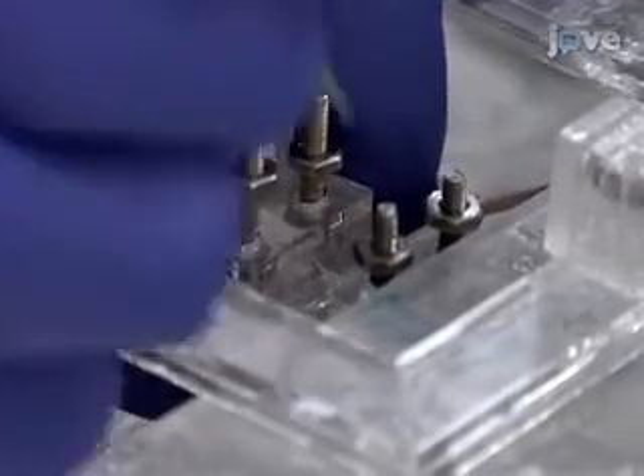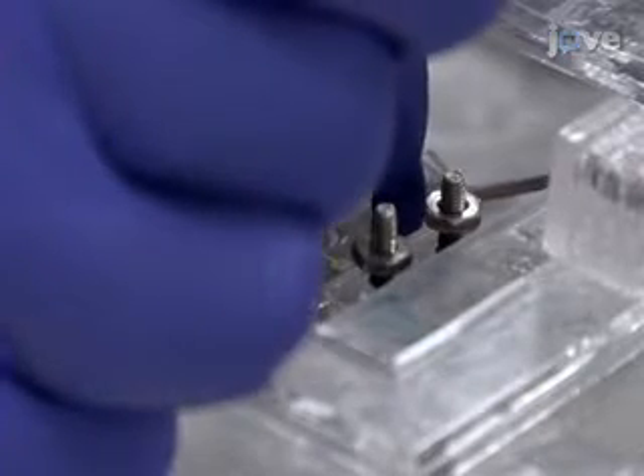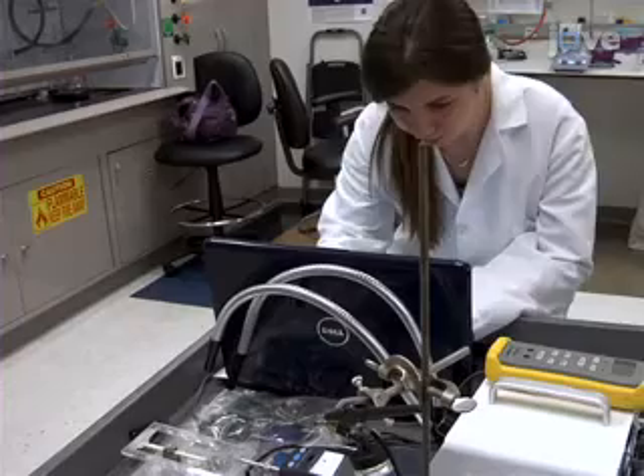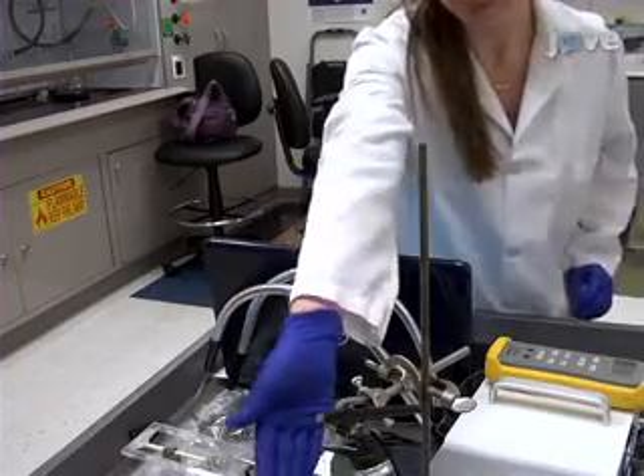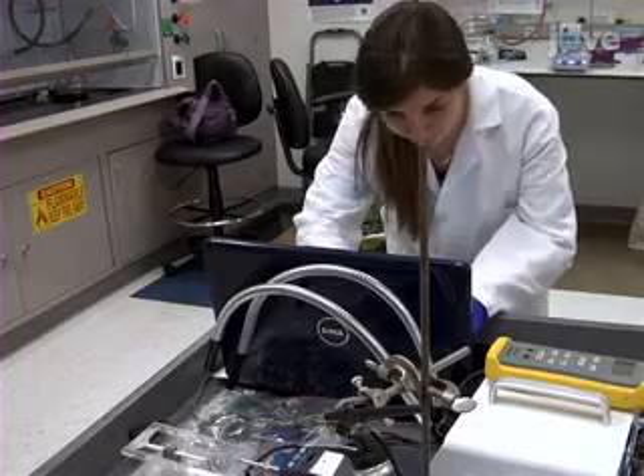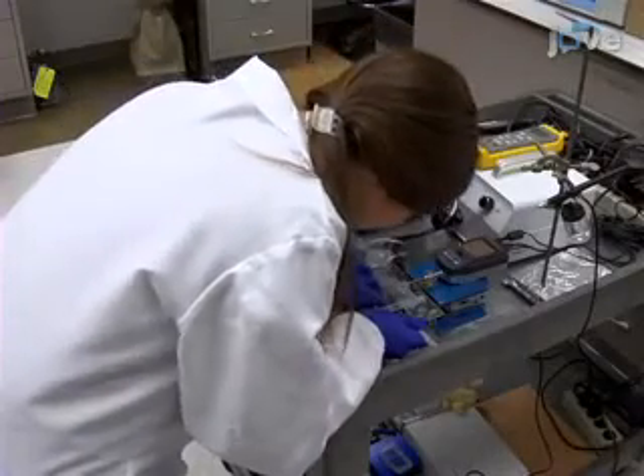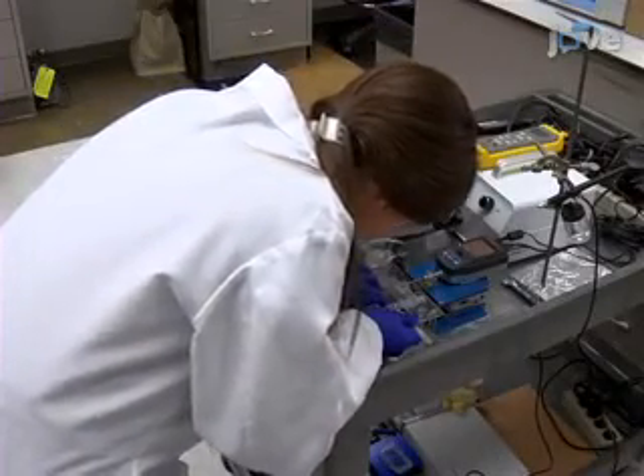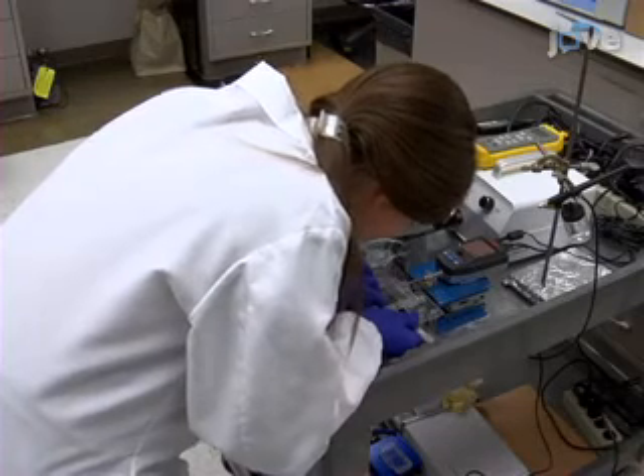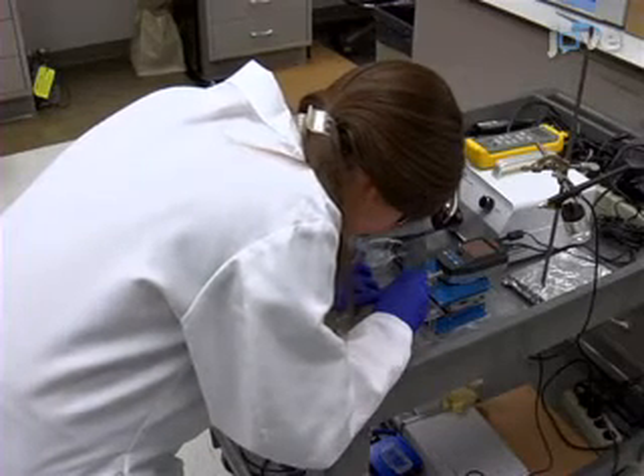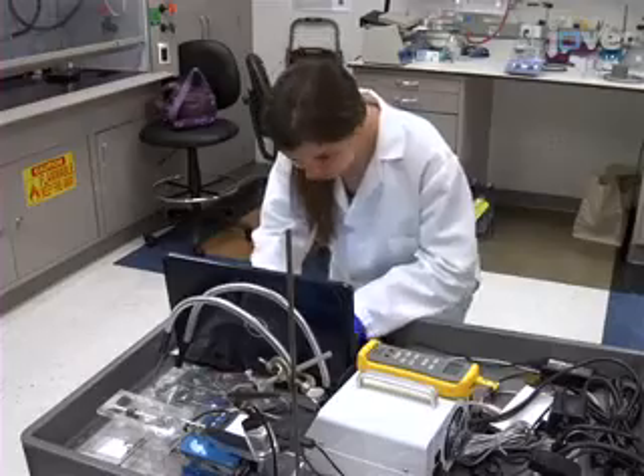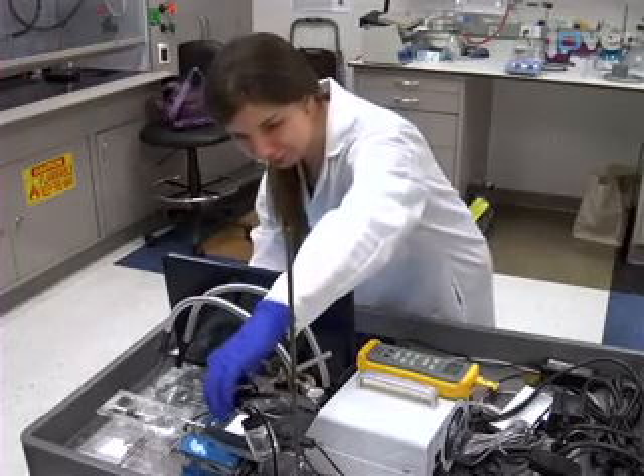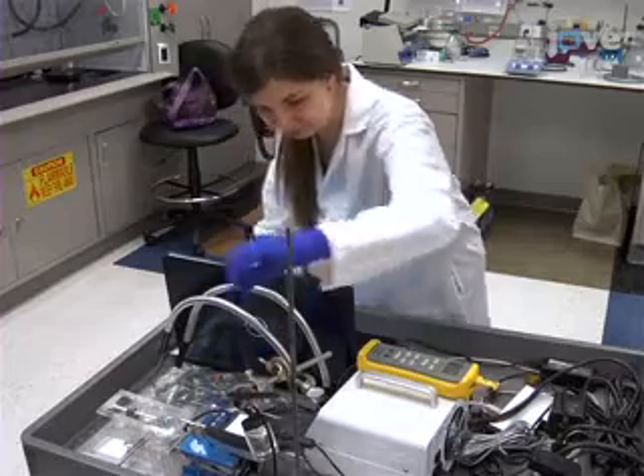Quickly load a sample into the microtensile tester and begin cyclic microtensile testing with the airbrush off while the sample dries under ambient conditions. The Young's moduli found from this data will indicate how quickly the sample dries under non-controlled conditions. Next, load a second PBS saturated setup sample into the microtensile tester and begin cyclic microtensile testing with the airbrush on. Here, the calculated Young's moduli will indicate how quickly the sample dries under controlled humidity conditions.